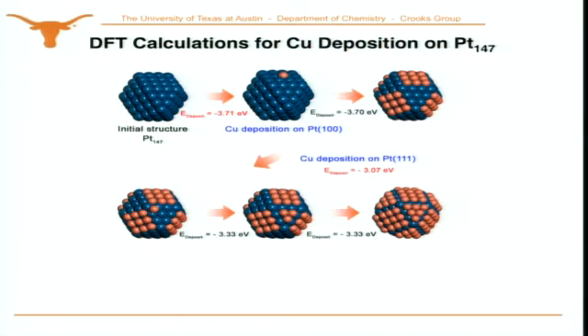Okay, so here's the DFT calculations. Here's our particle. We're going to first put one atom on this square facet here, and the energy calculated for that is minus 3.71 eV. It turns out that putting all the other atoms on here has an energy of adsorption approximately the same as this value. So as soon as we get one atom on here, all of the others go on immediately at that same potential.